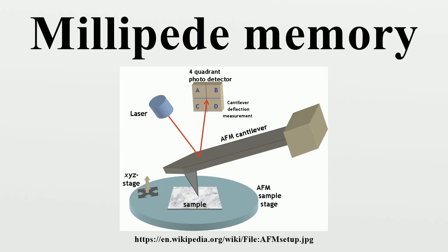Each probe in the cantilever array stores and reads data thermomechanically, handling one bit at a time. To accomplish a read, the probe tip is heated to around 300 degrees Celsius and moved in proximity to the data sled. If the probe is located over a pit, the cantilever will push it into the hole, increasing the surface area in contact with the sled, and in turn increasing the cooling as heat leaks into the sled from the probe. In the case where there is no pit at that location, only the very tip of the probe remains in contact with the sled, and the heat leaks away more slowly. The electrical resistance of the probe is a function of its temperature, rising with increasing temperature.